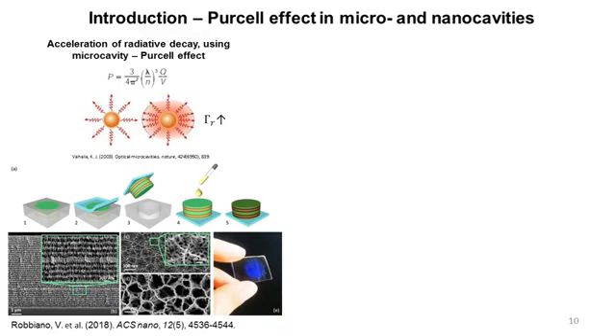The first way to increase the photoluminescence intensity is to increase the quantum yield of quantum dots. Indeed, when interacting with molecules of the environment, especially in the case of bioimaging, the quantum yield of photoluminescence of quantum dots usually decreases several times due to the appearance of additional non-radiative excitation relaxation channels.